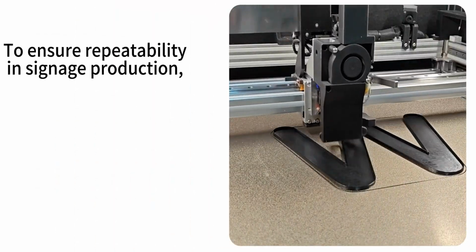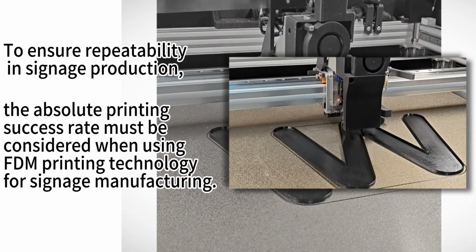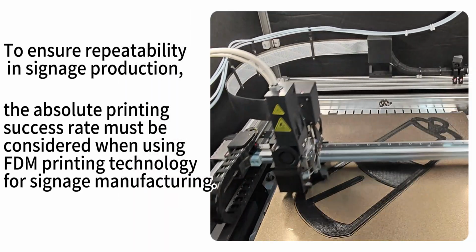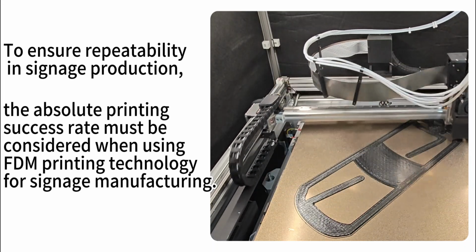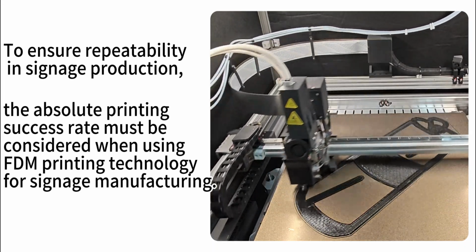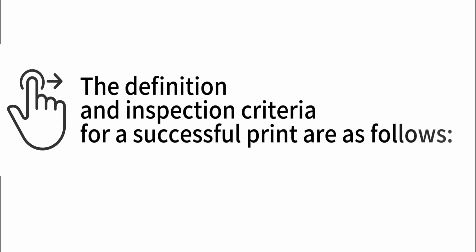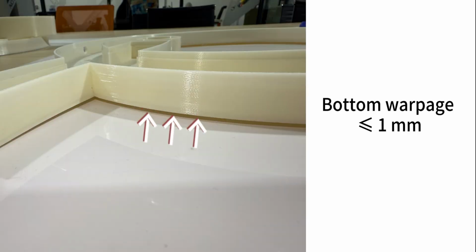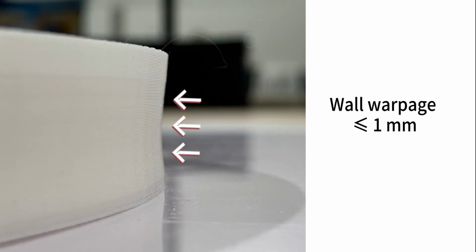To ensure repeatability in signage production, the absolute printing success rate must be considered when using FDM printing technology for signage manufacturing. The definitions and inspection criteria for a successful print are as follows. Bottom warpage is less than or equal to 1 millimeter. Wall warpage is less than or equal to 1 millimeter. Acrylic and step are assembled without gaps.